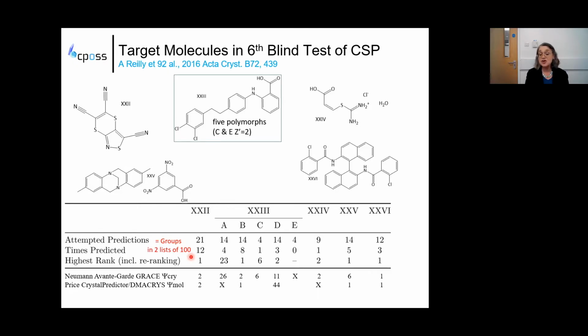However, the theory that the known structure should be the most stable does seem to hold, in that in most cases, at least one group got the known structure as the first, well, second to this one, apart from, of course, for polymorphs, where you can't all be the most stable. So this system of the polymorphs was very challenging. It was provided by one of the pharmaceutical companies, and not many people even attempted the polymorphs where you had 2 different conformations in the crystal structure. But anyway, that's the commercial company's success rate for that.